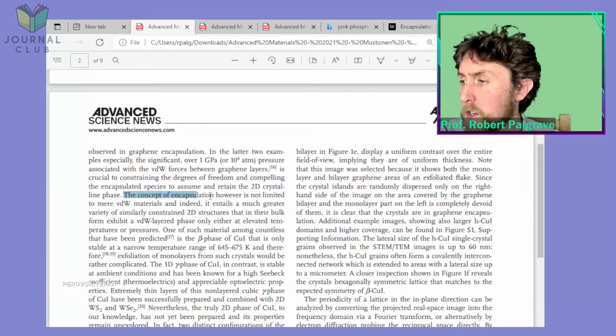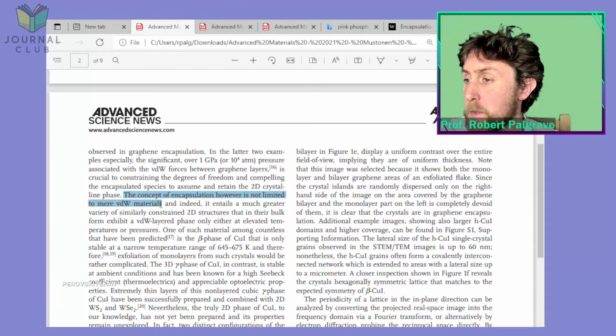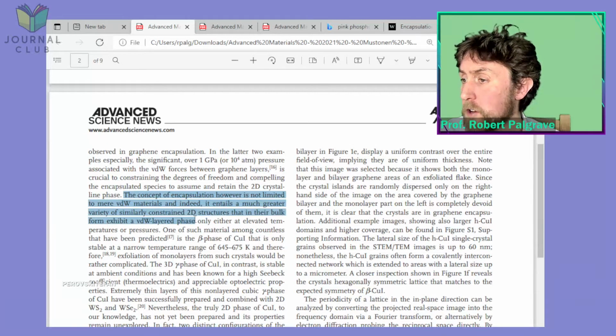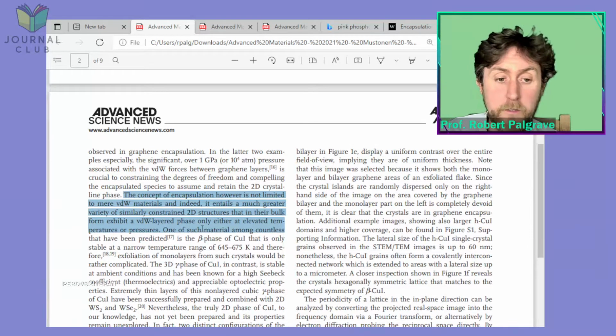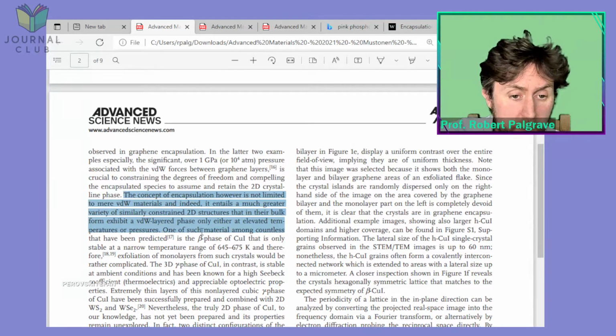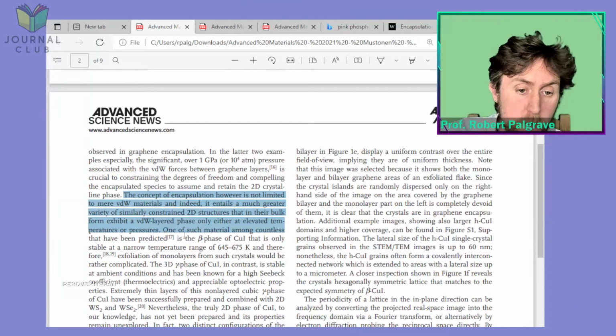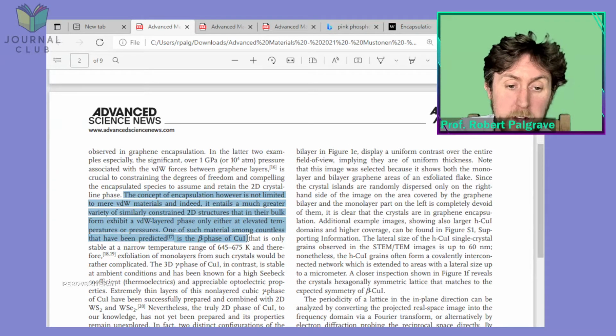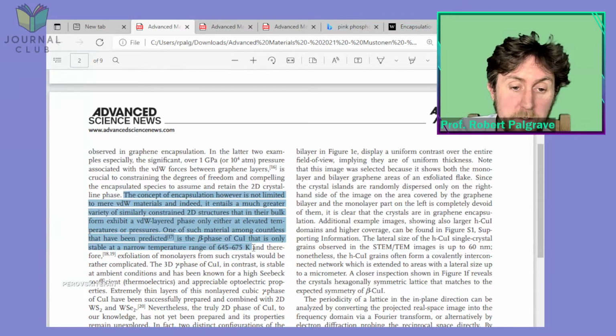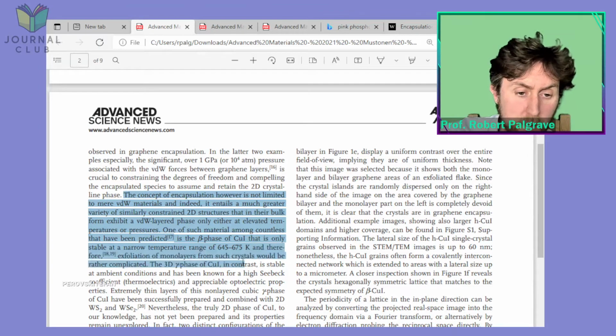So yeah, the concept of encapsulation is not limited to mere van der Waals forces. Indeed, it entails a much greater variety of similarly constrained 2D structures. In bulk form, many exhibit a van der Waals layered phase only at either elevated temperatures or pressures. One such material among countless that have been predicted is the beta phase of cuprous iodide that is only stable at a very narrow temperature range, 645 to 675 Kelvin. And therefore exfoliation and monolayering in such crystals would be rather complicated.